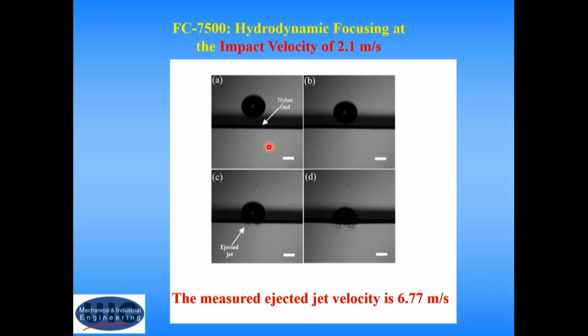So what you can do then is measure the velocity of these ejected jets coming after the membrane, and the result is puzzling. The impact velocity here is 2.1 meters per second, whereas the outflow velocity is 3 times higher than that, 3 times higher. And this is all after all these viscous losses in flow in tiny pores. And that's exactly what I told you. This is hydrodynamic focusing.